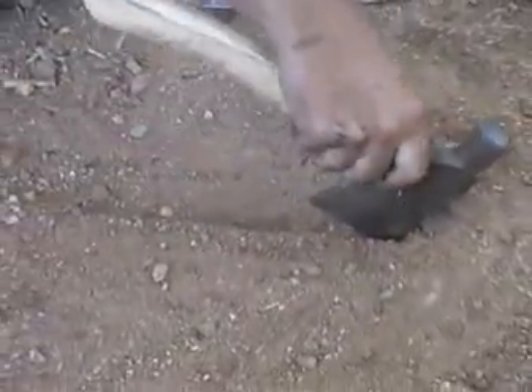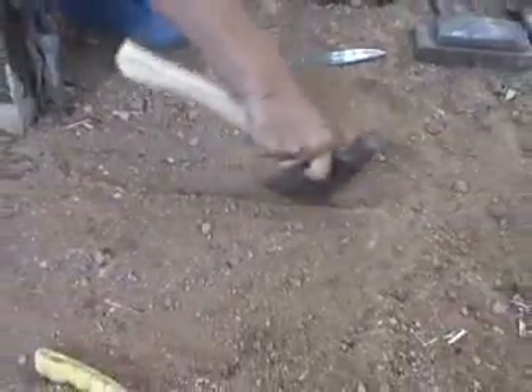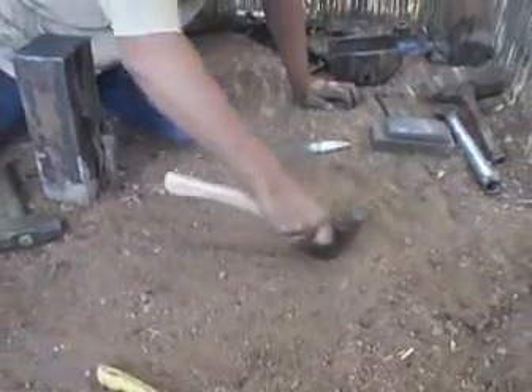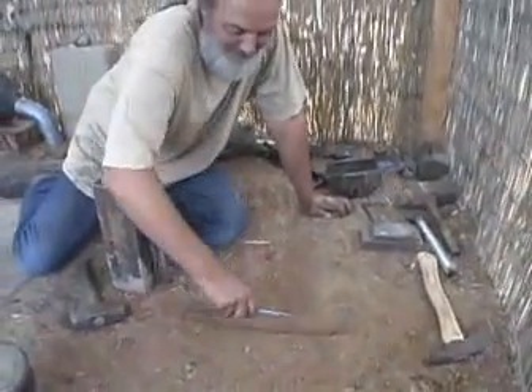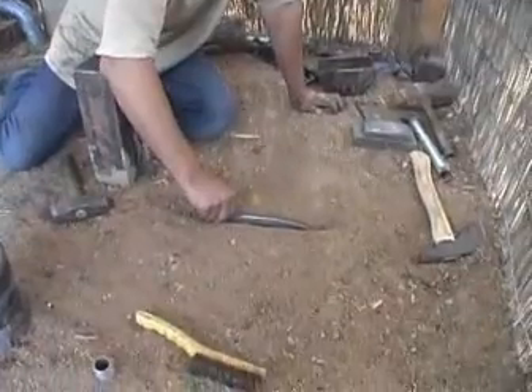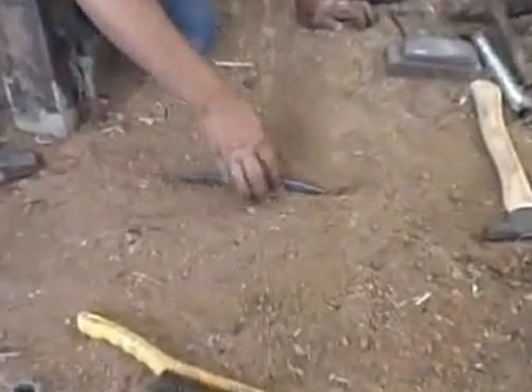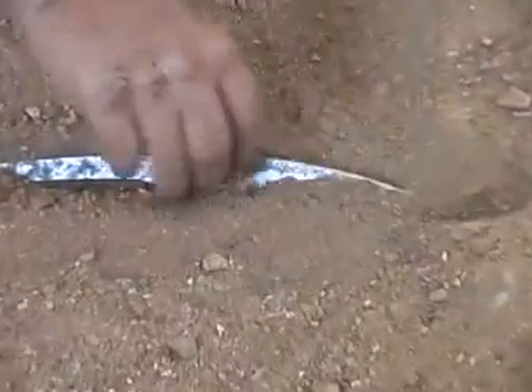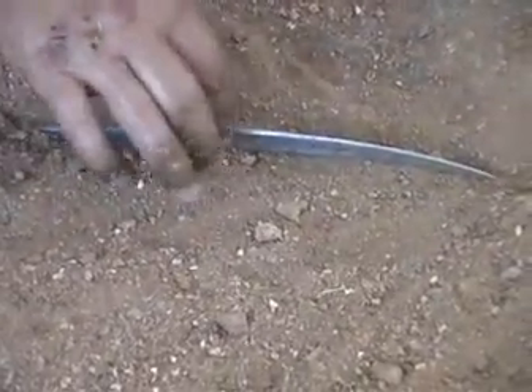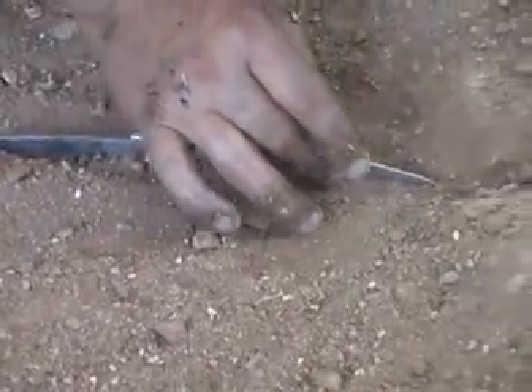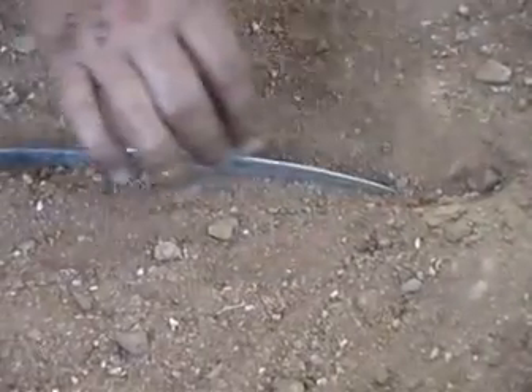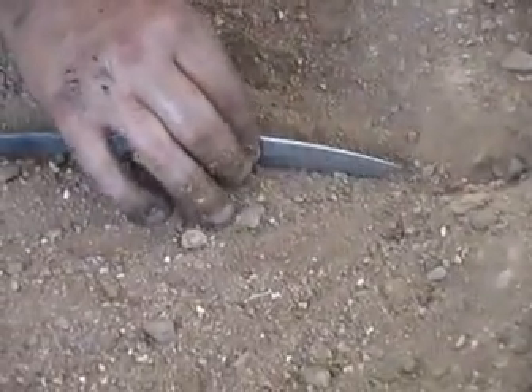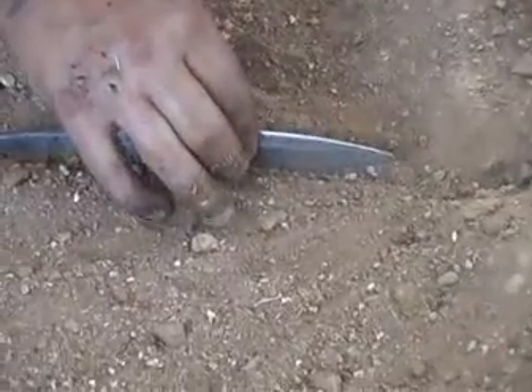So I make a groove in the earth, just a shallow little groove with an old beat up hatchet, and set my edge down into it. Put a little bit of loose stuff in there, and I'm going to grab it with some real thick, heavy-ended tongs that are heated up in the forge, and pinch the back with these hot tongs and temper the back and pull it up a little bit as I do that and let the heat travel down towards the edge.